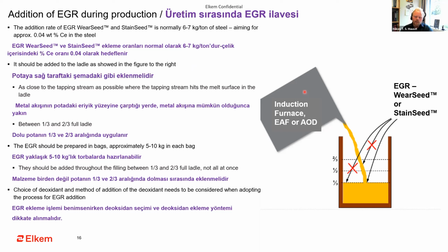So typically here you have your induction furnace, your electric arc furnace, or your AOD converter, and you start to tap steel into your ladle. So here we have the ladle. Usually you should try to fill it up about 1/3 with steel. And then you should start to add the EGR wear seed or stain seed.